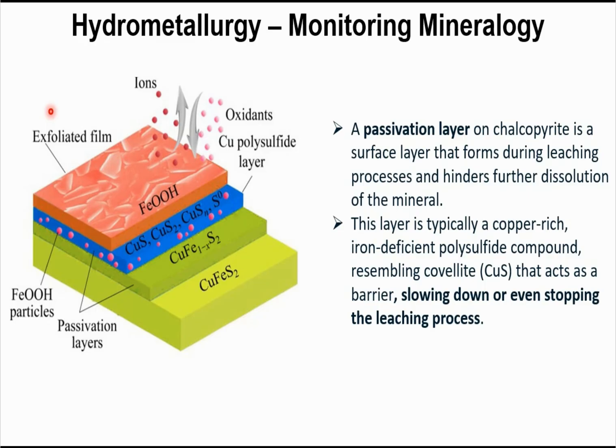So we have figured out a way now to monitor and detect the presence of passivation layers, and not shown here, but I'll hit on next year probably, is the fact that we can now relate that to the pH, the acidity of the lixiviant, and mining companies that we've worked for have changed that composition so they can eliminate the formation of passivation layers.